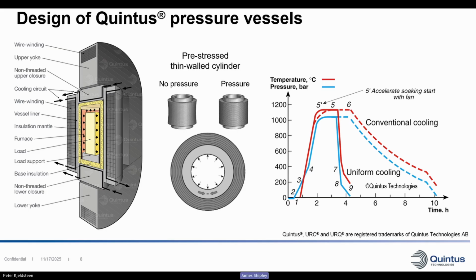So it's above 1,000 bar or 100 MPa. And with this and a furnace inside, we're heating the material, softening the material a little bit, and getting it to relax, so that the pressure can then densify and remove voids. So I think densification is the main area that everybody knows about. But there are really, for us, four main areas for hipping today.